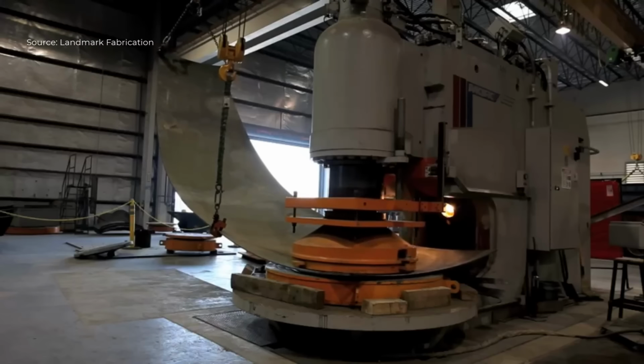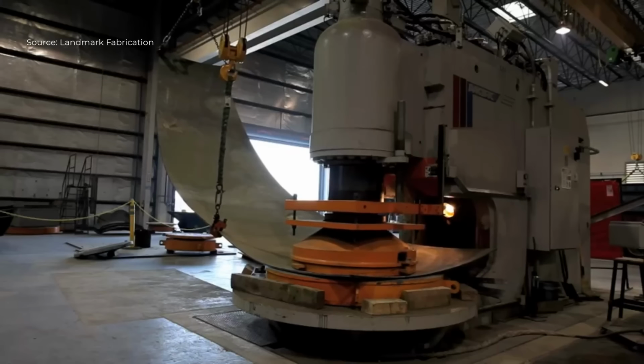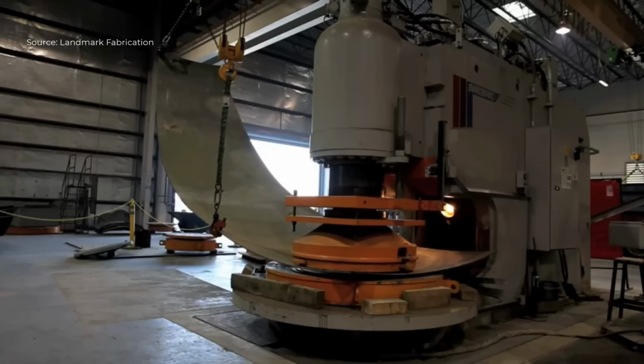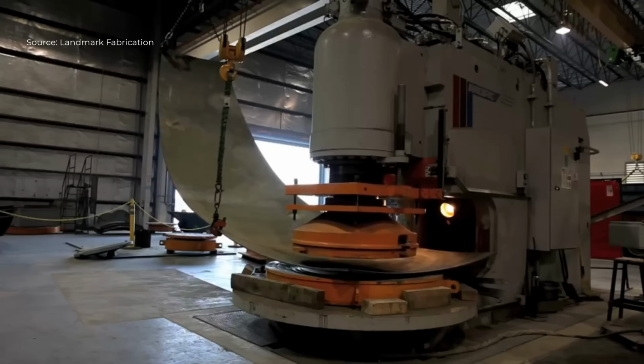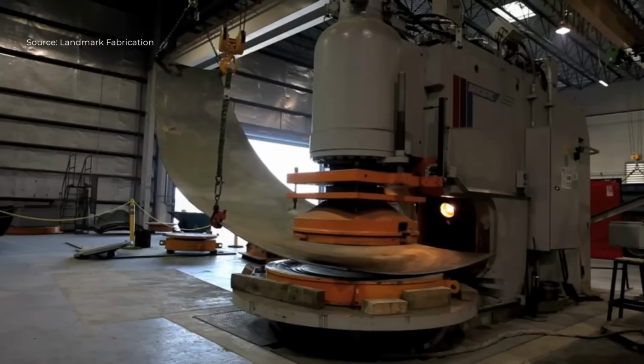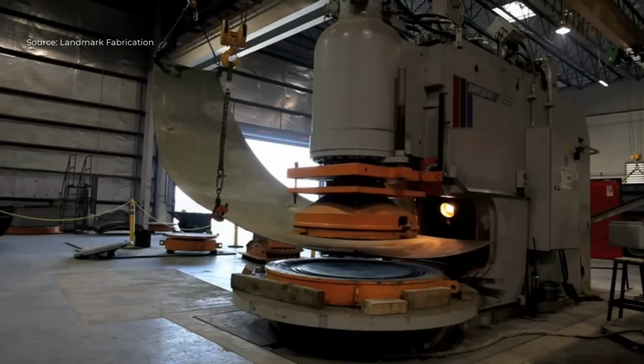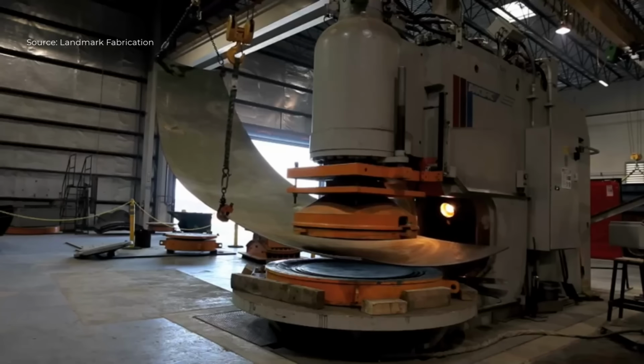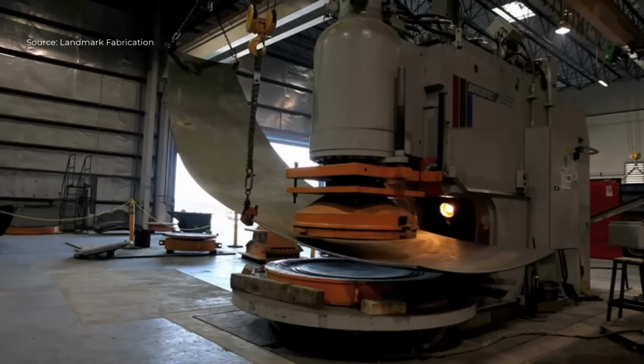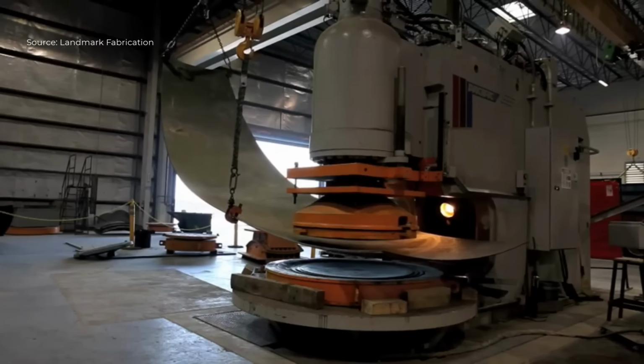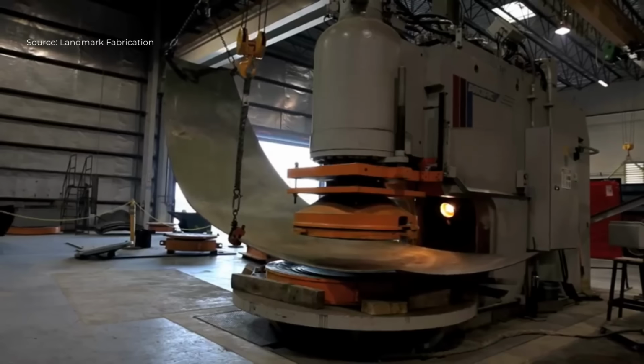Landmark's 750-ton Bliss mechanical press is used to form a 1/4, approximately equals 6 mm, steel plate into the upper ball segment of a 250,000-gallon elevated spheroid storage tank. The process begins with a flat plate of precisely measured thickness, cleaned and prepared before forming.